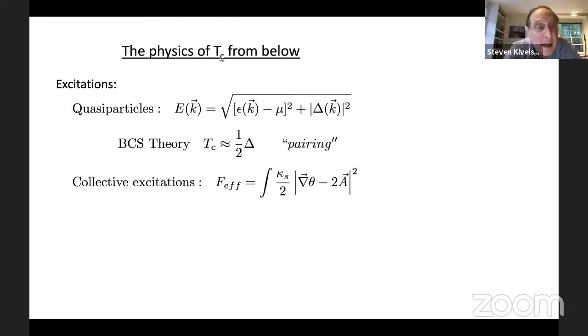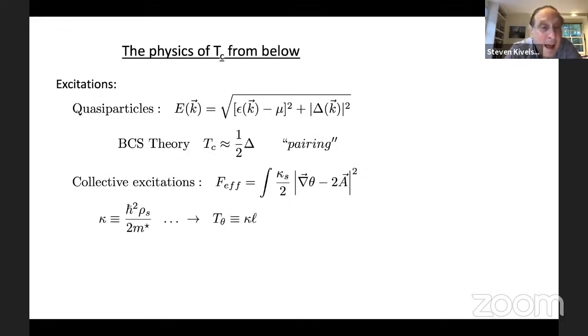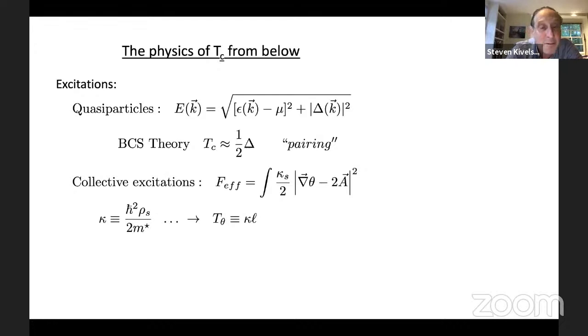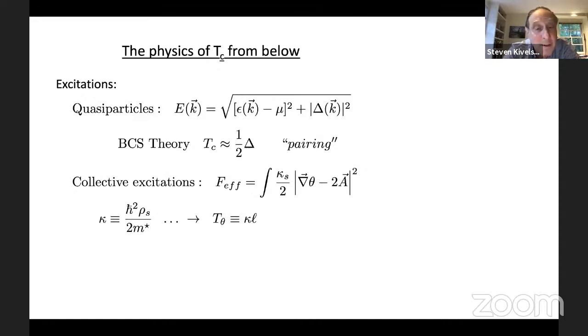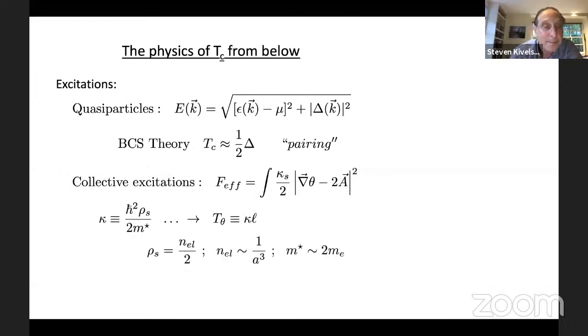The temperature scale T-theta is kappa times some microscopic length L; when temperature reaches T-theta, phase fluctuations become sufficiently violent to likely destroy superconducting coherence. A crude estimate takes the superfluid density to be half the density of electrons (since they pair up into Cooper pairs), takes the electron density as roughly one over a lattice constant cubed, and the effective mass as twice the electron mass. This gives T-theta on the order of 10⁴ Kelvin times one over the lattice constant in angstroms and the length L in units of the lattice constant — obviously a very high temperature that has nothing to do with TC in conventional superconductors.